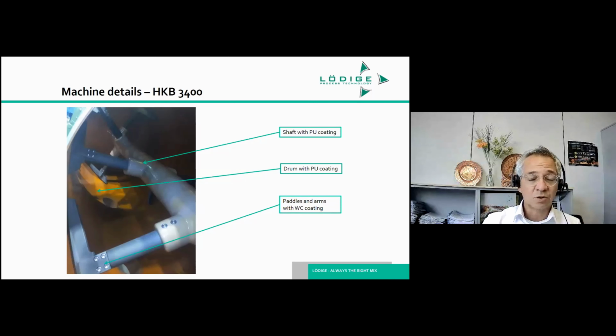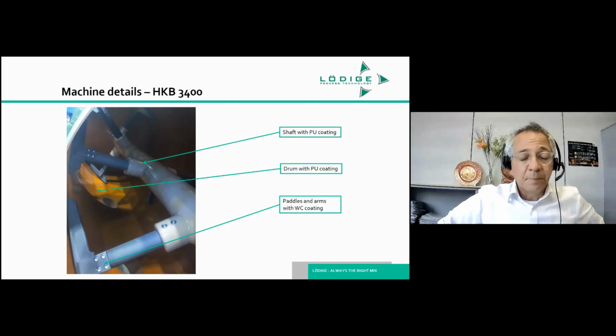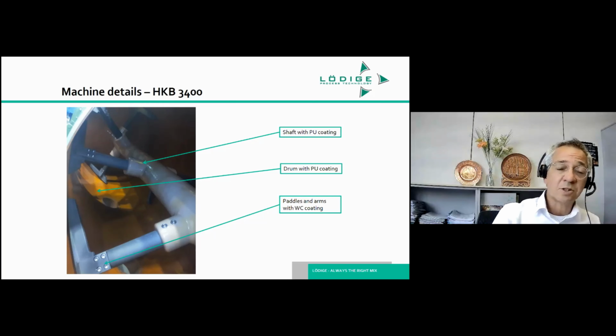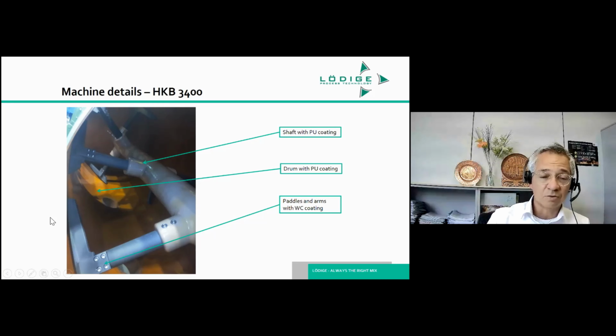And here again is a picture of the counterpart. It is a paddle mixer. You can see from a design point of view, individual paddles are far easier to fabricate than the complicated ribbon structure. Both items mix and blend equally, so customers can either choose the ribbon or the paddle, or even have a mixture of both, depending on how they want to do maintenance, cleaning, and inspection. But here, again, emphasis is put upon the coatings. Again, polyurethane coating on the drum and on the mixing shaft, and tungsten carbide on the mixing tools, and the bolts in the shadow of the mixing processes are left untreated as before, because they don't really get that much into contact with the product.